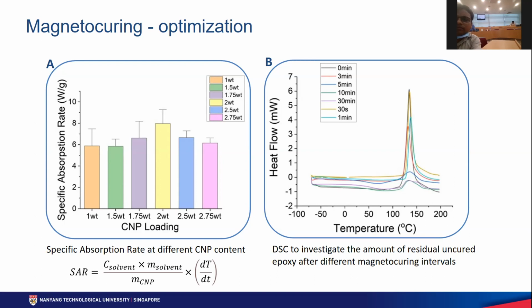So on the right, I have the plot of the specific absorption rate. Basically, it tells us how well our composite is dissipating heat at different amounts of nanoparticle loading. Surprisingly, for this specific system, we don't find any statistical difference between the specific absorption rate for formulations between 1 weight percent and 2.5 weight percent. The maximum obtained was around 8 watts per gram, but this is a very interesting result.